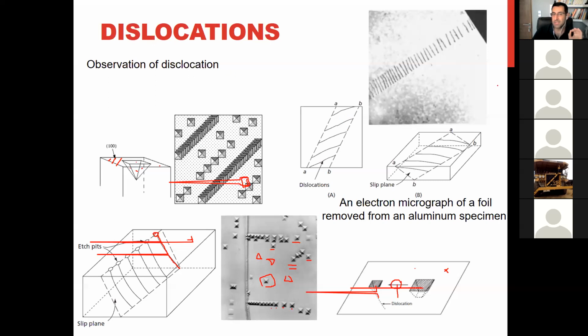Also, we can see them by electron microscopy. This is the observation of dislocations beneath the electron microscope, and it is something like this. We make a foil. This is the case of aluminium. In this foil, AABB is a part of a slip plane. Inside this slip plane, we have dislocations: one line, two, three, four, five dislocations. But when you see it with electron microscopy, you are seeing two dimensions. It means you are seeing it like this. So all of them are dislocations that we can see with electron microscopy.